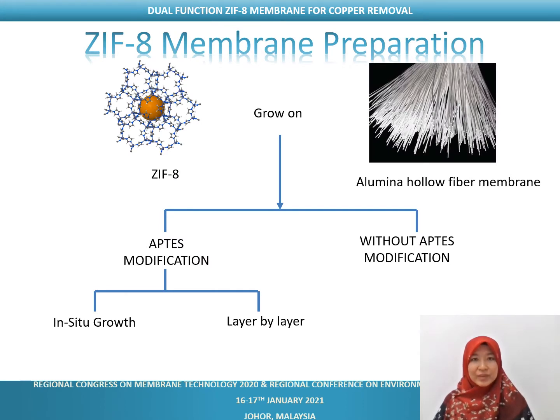In this study, the preparation of ZIF-8 membranes were done with and without the modification of alumina substrate with APTES as linker. This is to determine the effects of APTES on the morphology of the ZIF-8 form.